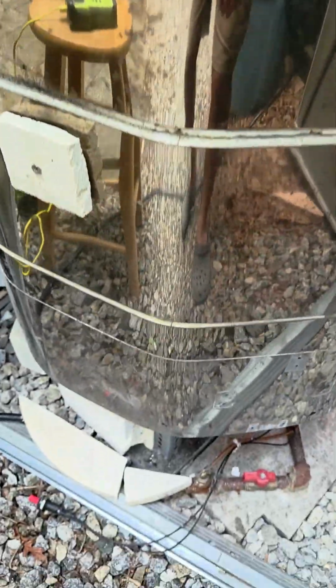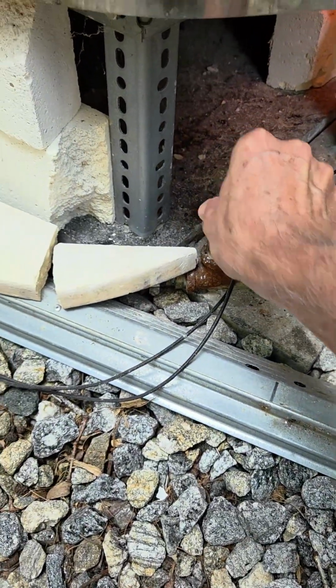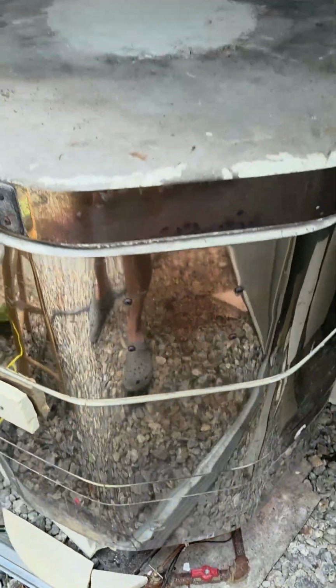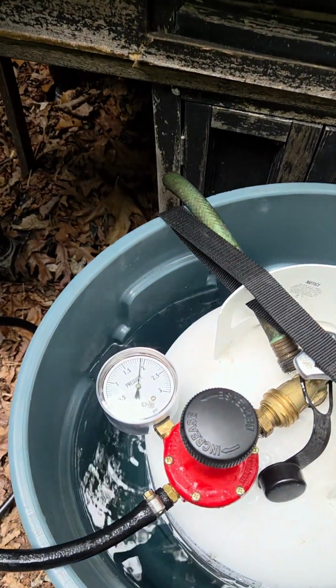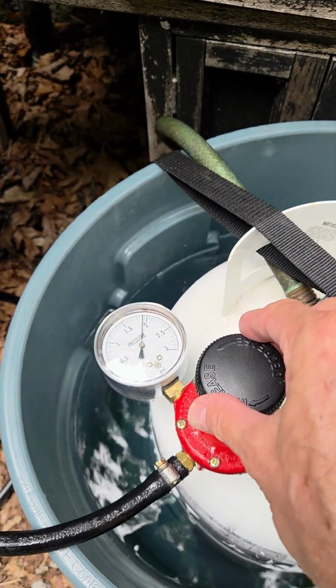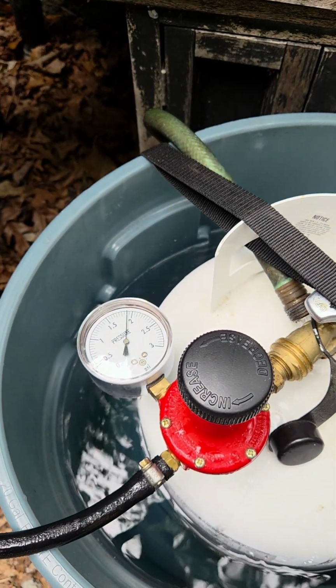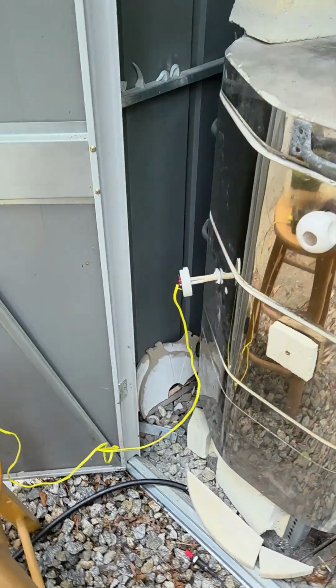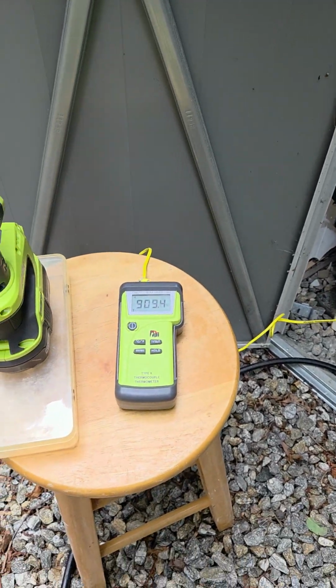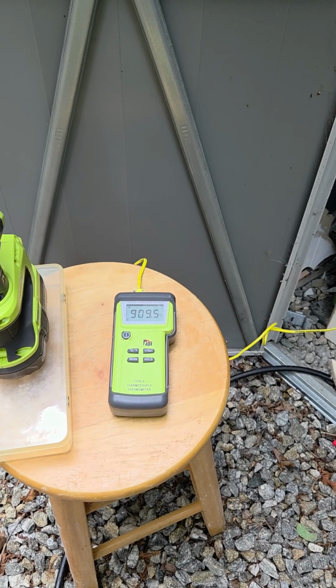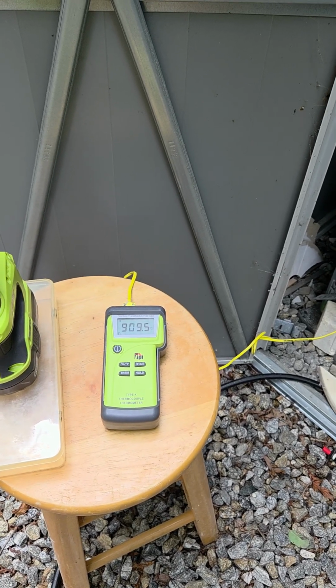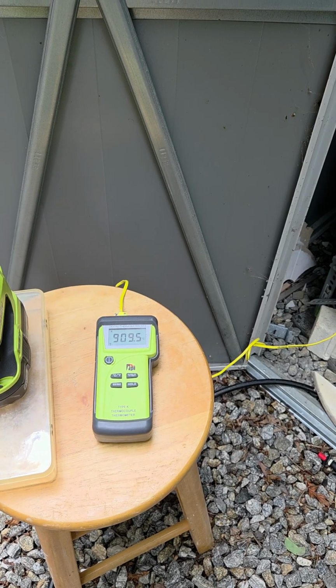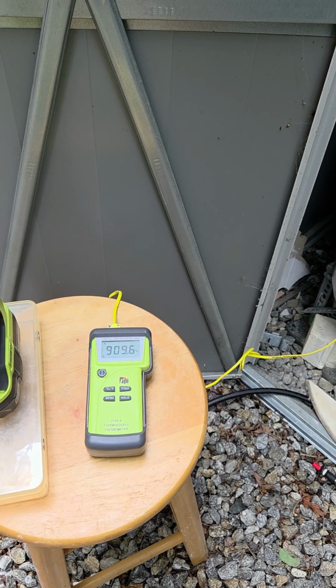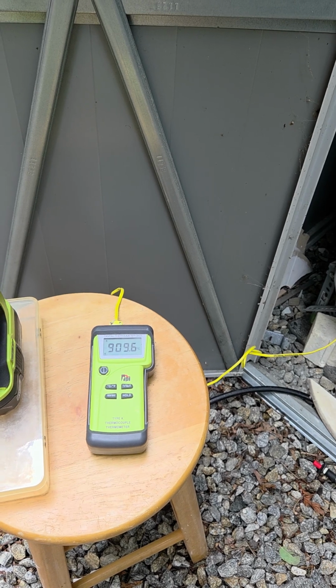And at this point I can go ahead and turn the pilot off because it's red hot, and even if the wind were to blow it out, there'd be no issues. And I've got this set on approximately 1.9 psi. So now I'm just going to monitor the temperature for about 40 minutes. This is for body reduction. And the range is about 900 to 930 degrees is what I try to do over a 40-minute period.